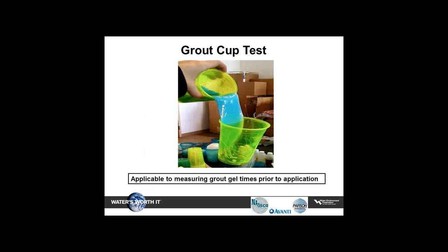And this is simply by taking a portion of component from each of the gel components from the application equipment and doing a quick gel test, which is a matter of pouring one material into the other material and back and forth, and then just basically getting a time on how fast it gels. Very, very simple test out in the field, but it will tell the inspector that, yes, the material at this point in time will gel, and he can document that. So this is applicable for measuring grout gel times prior to application.